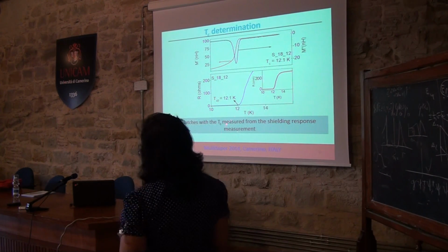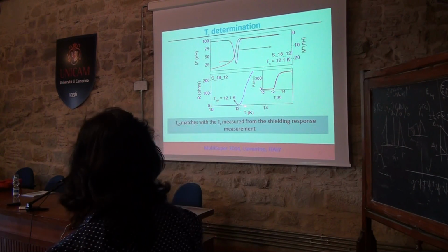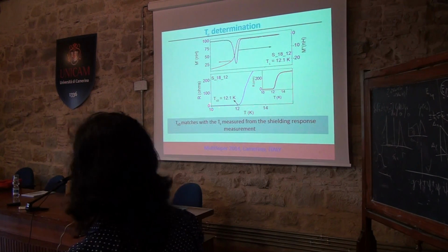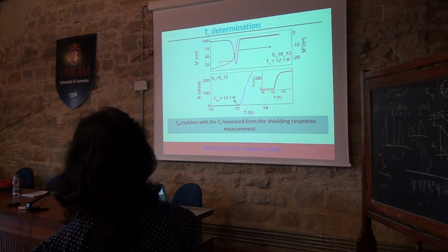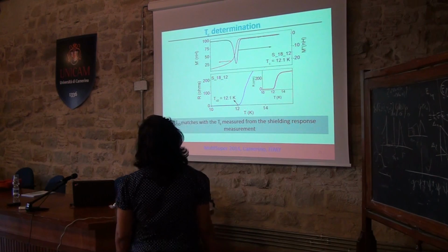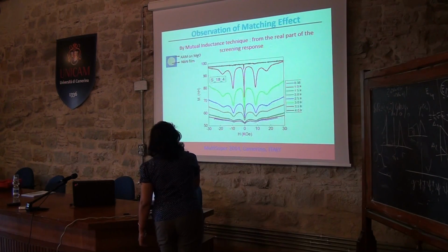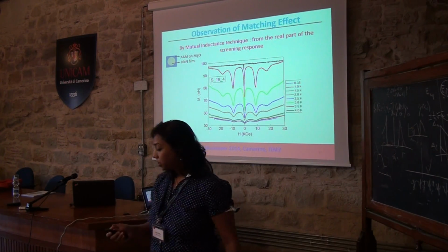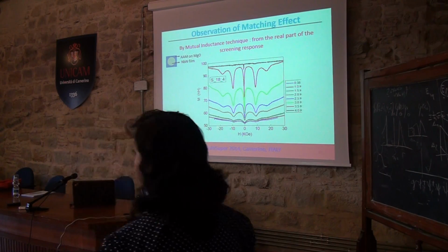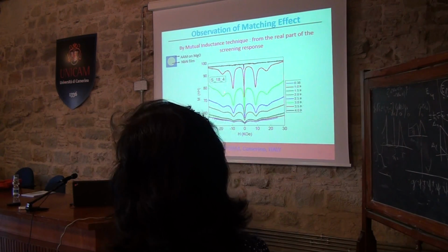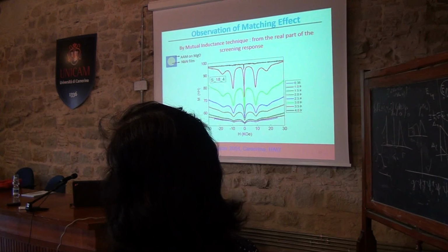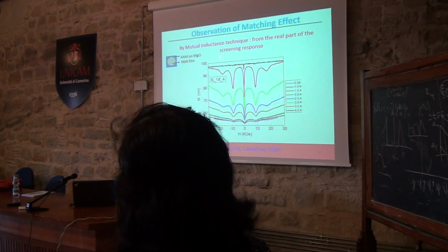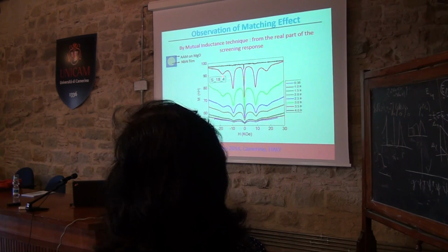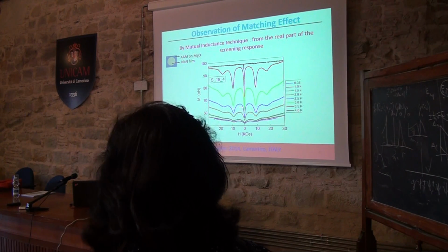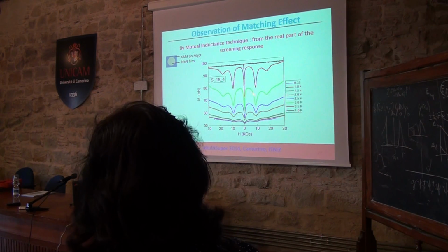We also checked that the TC which we measured by a mutual inductance technique matches with the one which we measure by magnetoresistance, and it matches quite well with the zero resistance. Okay. So now we did the mutual inductance measurement as a function of magnetic field, and there you are. This is a measurement done on a sample which has got 18 nanometer pore and a TC of 4 Kelvin, and you can see these oscillations with magnetic field.